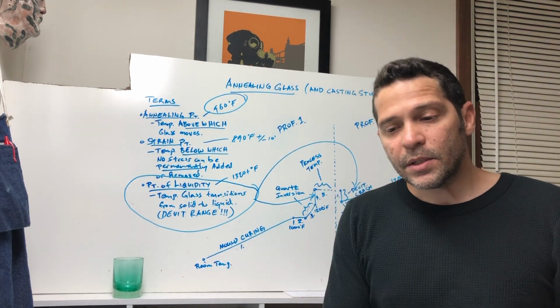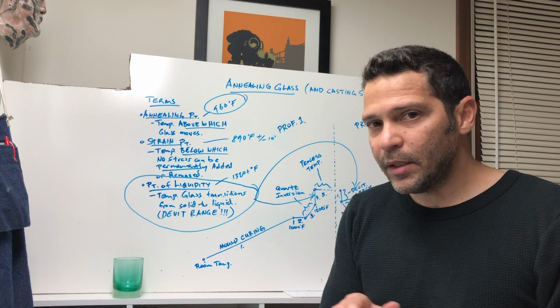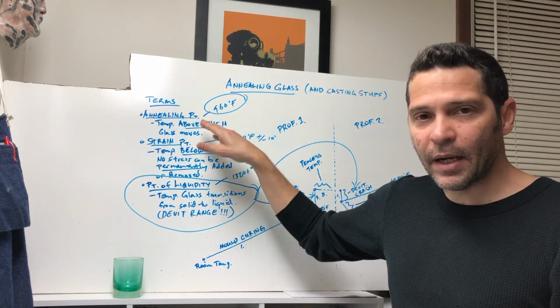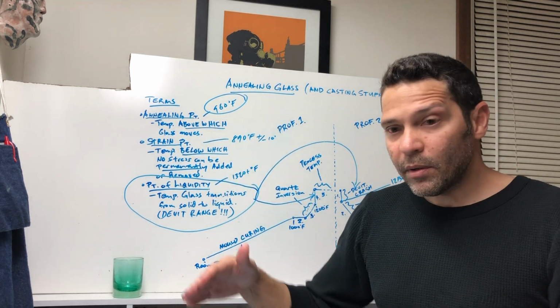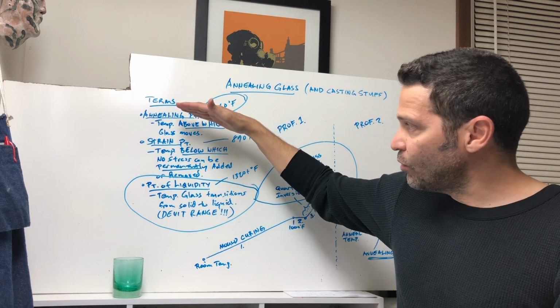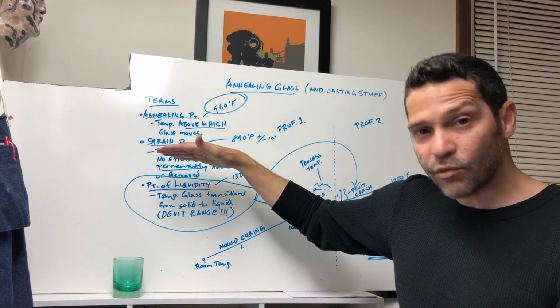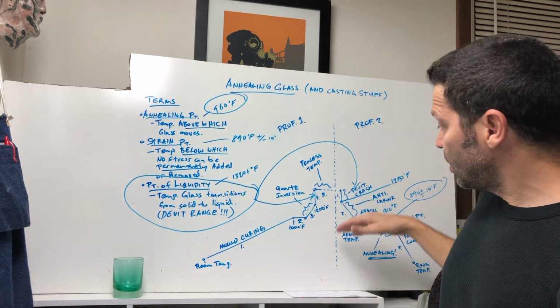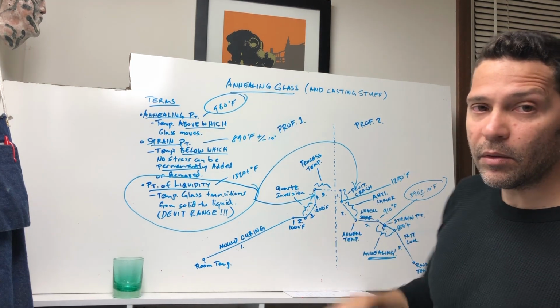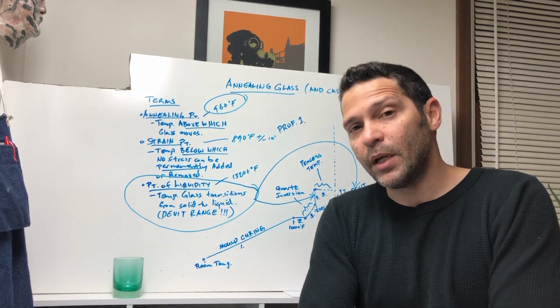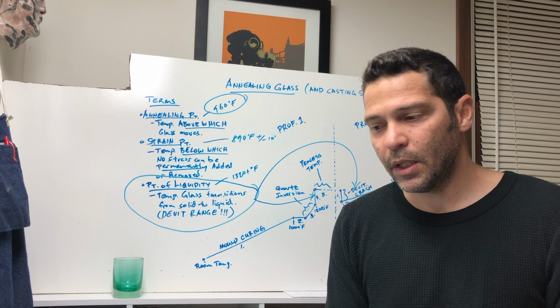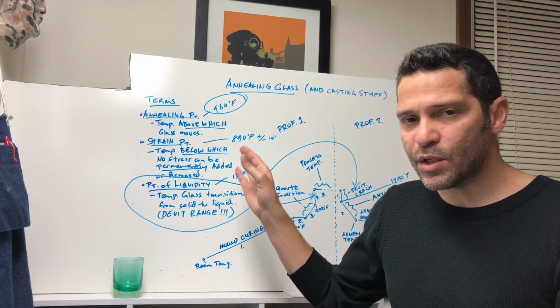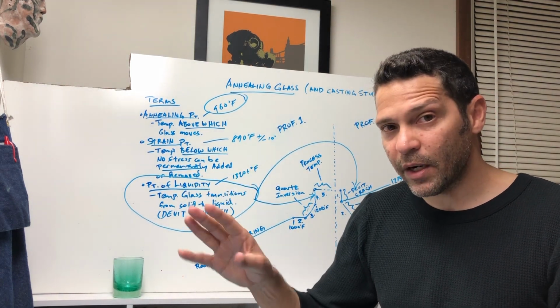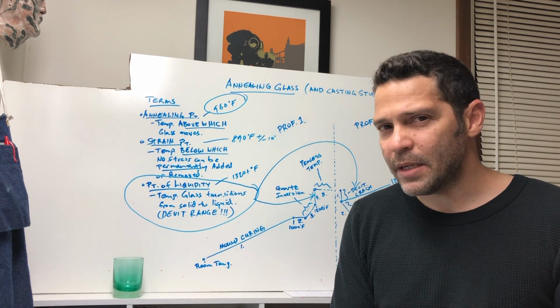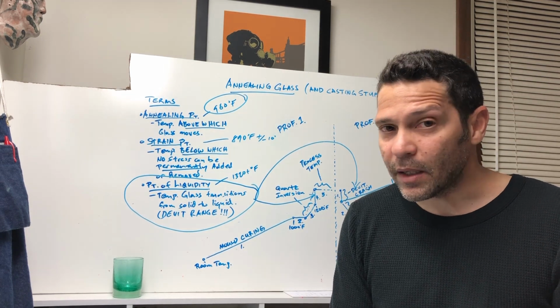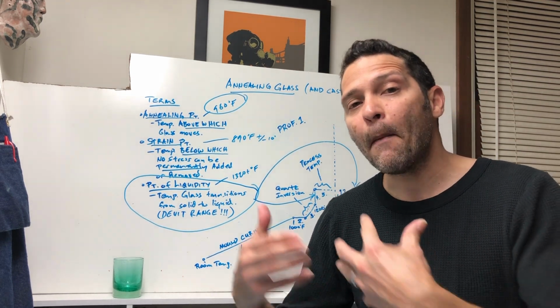And for us, at least the way I teach it, the annealing point is not the set annealing point of 960. Remember, the annealing can happen anywhere within the range between the annealing point and the strain point. So I'm gonna anneal as per Bullseye's recommendations closer to the strain point. I don't quite go at 900 because Spectrum is plus or minus 10 degrees Fahrenheit at 890, so I do about 910. That still saves me a lot of time and allows me to anneal a thing better.